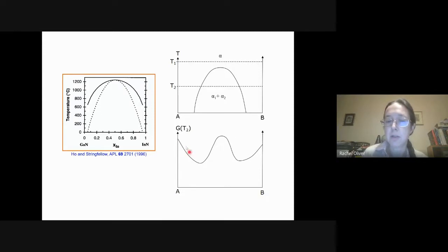But if I lower the temperature, the energy versus composition curve has this kind of W shape with two minima. And what that means is that if I talk about a composition X dashed, it can lower its energy by splitting up into regions of composition X1 and regions of composition X2, because X dash has a really high energy, but the other two compositions, which are lower and higher in B than X dash, have much lower energies, and by having a bit of each, we can have a lower overall energy. Now, there's another line on this diagram, which is this dashed line. And the dashed line is defined not by these minima on the curve, but by these two points of inflection.